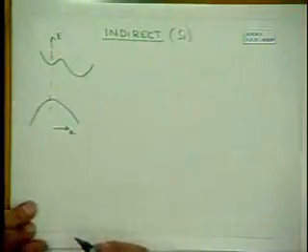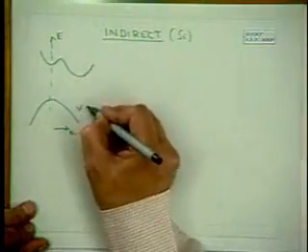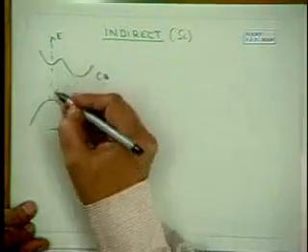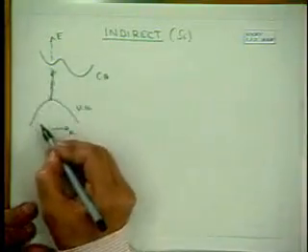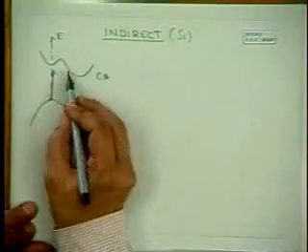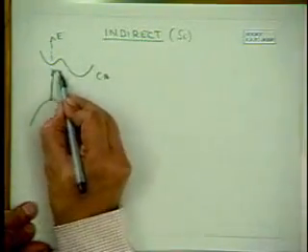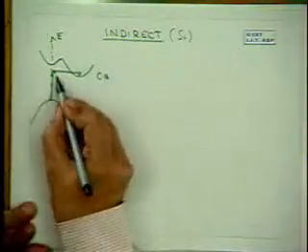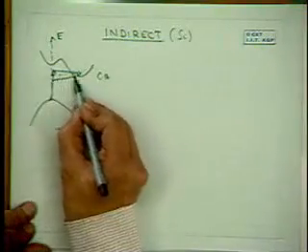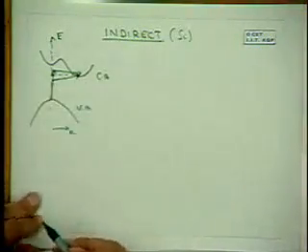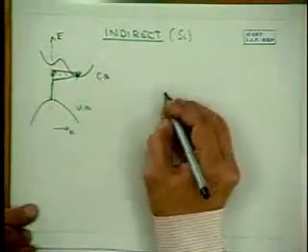In order to get transfer of electrons from the valence band to the conduction band, absorption of photon energies must be followed by either absorption or emission of a phonon. This is emission of a phonon, and this corresponds to absorption of a phonon.